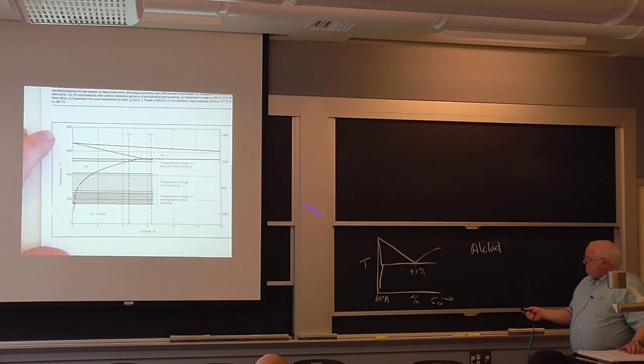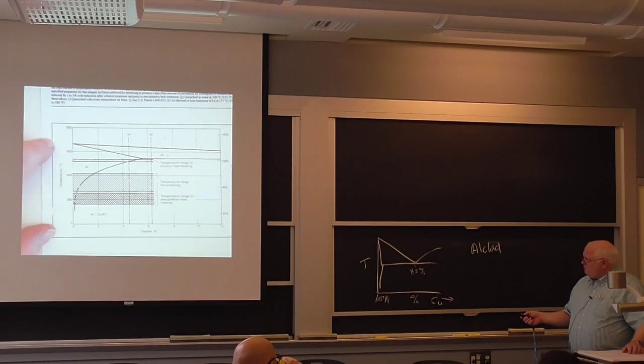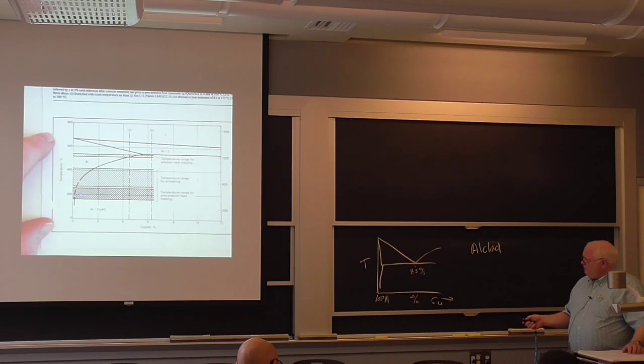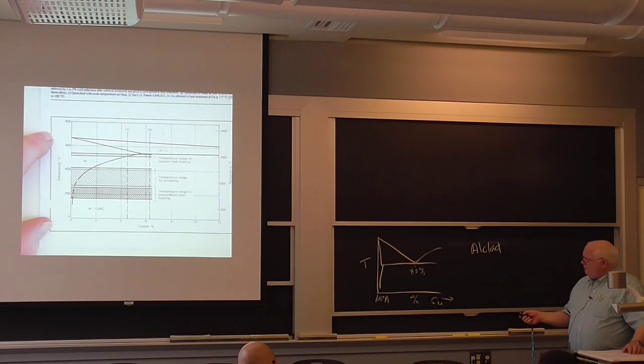So here's that type of phase diagram, and this is aluminum copper, and you have to solutionize by bringing the stuff up while it's still solid in this range, and then you quench it down to low temperature, and then you can precipitation heat treat in this range. If you're going to anneal it, you use these ranges of temperatures. This is 400 centigrade, 200 centigrade, 500 or 400 Fahrenheit here.